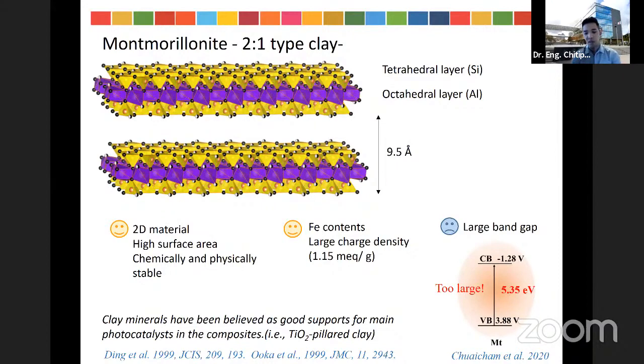But the problem of clay for photocatalysis is the large energy band gap, as it mostly belongs to the non-electron-conductive materials. So normally people believe that clay is just a good support for the main photocatalyst. But in our case, we are going to show a new role of the clay mineral for the photocatalytic reaction.